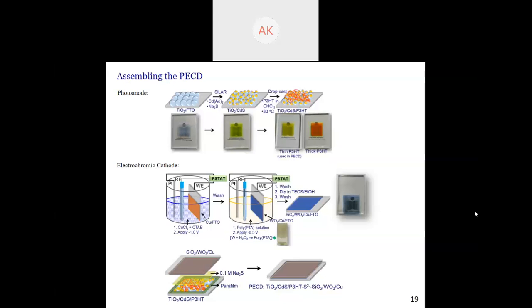What about the adhesion of the film coated by the author in the research work on FTO and ITO substrates? What is intended by adhesion? Like when I grow a film, coating it by doctor blading and then annealing it, the film pretty much sticks to the FTO surface, because FTO, fluorine doped tin oxide, has a rough surface. But what about the adhesion of the coated film? Whether it is peeled out easily or adheres in a proper manner? No, it is not peeled out, sir. It is sticking till the last, because sometimes we disassemble the cell and go for a few other characterizations. Sometimes when reviewers ask, it has not peeled and it is pretty stable over a couple of hours.